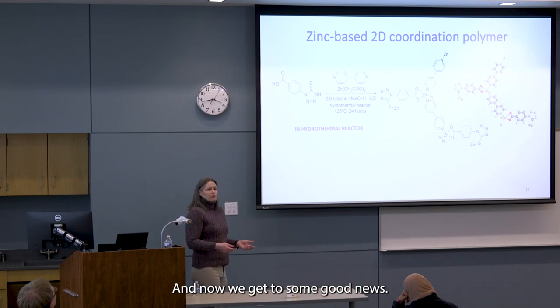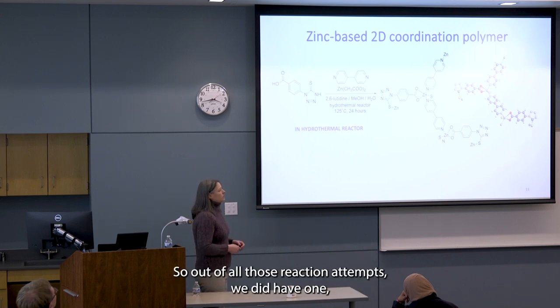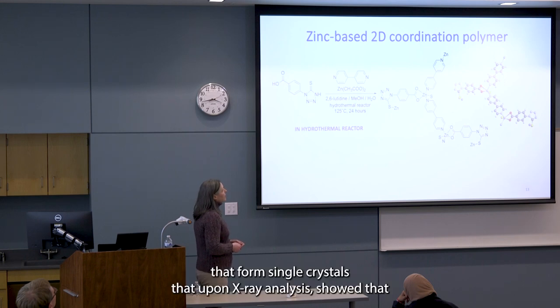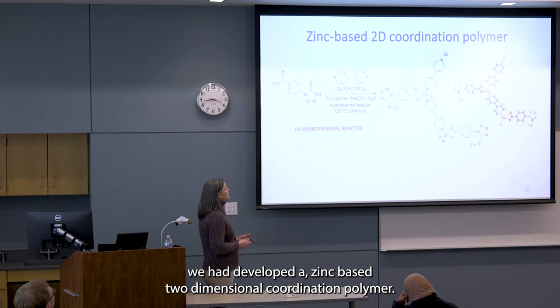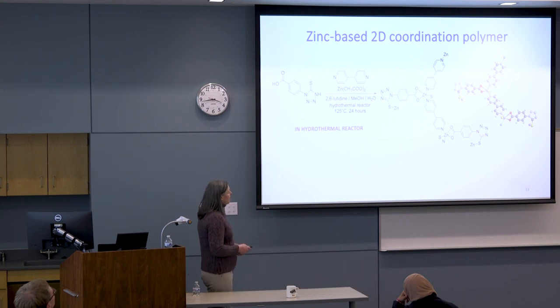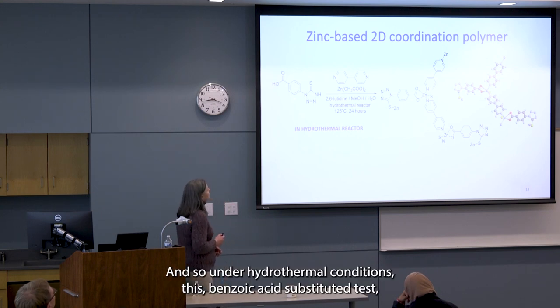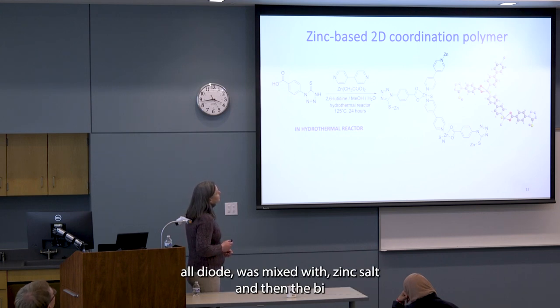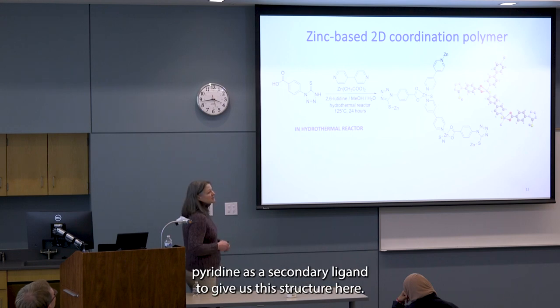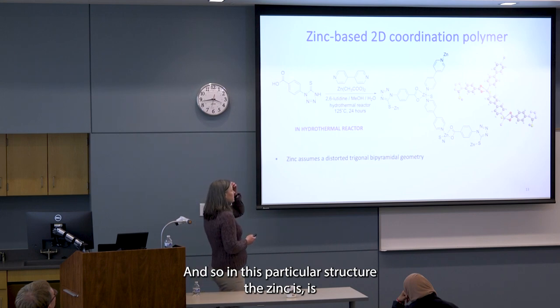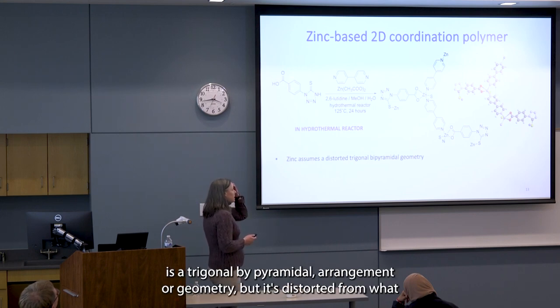And now we get to some good news. Out of all those reaction attempts, we did have one that formed single crystals that upon X-ray analysis showed that we had developed a zinc-based two-dimensional coordination polymer. Under hydrothermal conditions, this benzoic acid substituted tetrazole thione was mixed with zinc salt and then the bipyridine as a secondary ligand to give us this structure here. In this structure, the zinc has a trigonal bipyramidal geometry, but it's distorted from what it typically is.